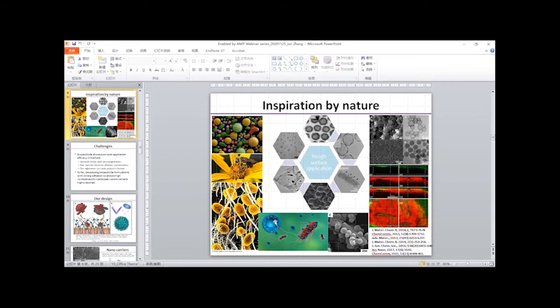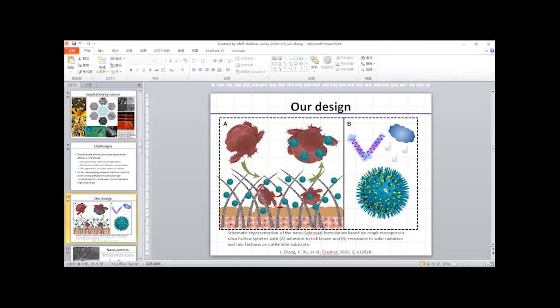Then we create the silica shell over this polymer sphere. And then we use the silica source and the polymer source to do a co-condensation. Their primary particles will randomly condensate on the outer surface of the silica shell and the polymer inner. When we remove the polymer by calcination, we create the hollow core, and a part of the polymer on the outer surface has been removed, creating the void spaces. The remaining silica primary particles will form this kind of spikes. These spikes are giving the surface property as a rough surface.